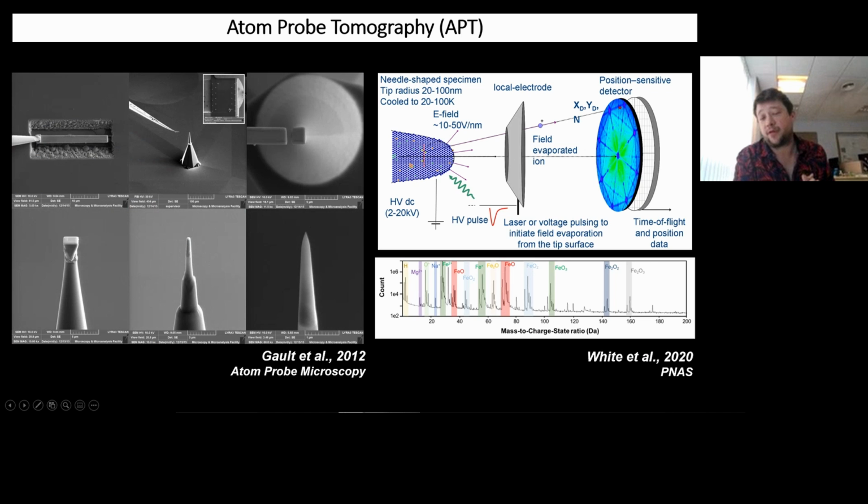So what is atom probe? Fundamentally, sample preparation is the key. Like I say, these samples are a 1,000th the width of a human hair, so teeny, teeny tiny. And to do that, we need to be targeting a feature of interest and then developing that for this analysis. So in this example here, we put down our platinum deposit in our FIB-SEM. We use a focused ion beam attachment to an SEM to extract and prepare these samples.